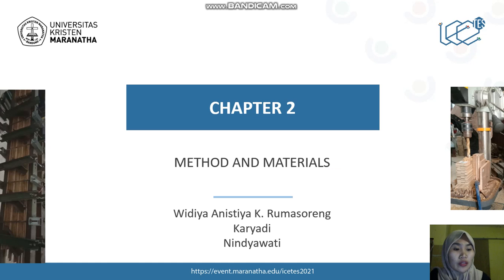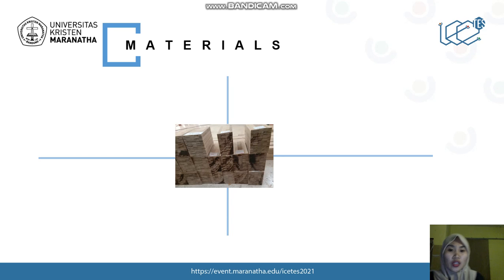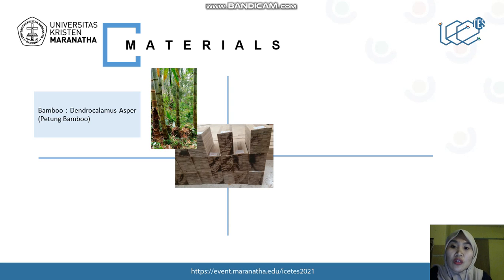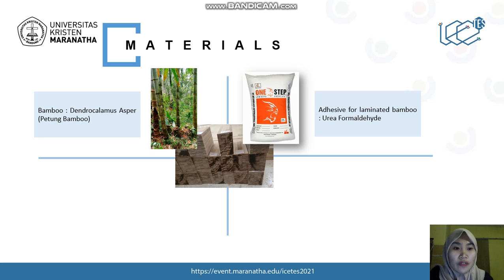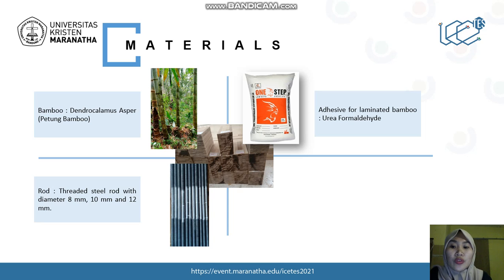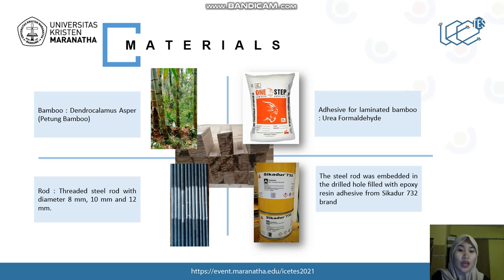Chapter 2, Method and Materials. To form the laminated bamboo, we use Dendrocalamus asper or petung bamboo. And as adhesive for laminated bamboo, we use urea formaldehyde from One-step glue brand. And for the rod, we use threaded steel rod with diameter 8 mm, 10 mm, and 12 mm. The steel rod was embedded in the drill hole filled with epoxy resin adhesive from Sikadur 732 brand.